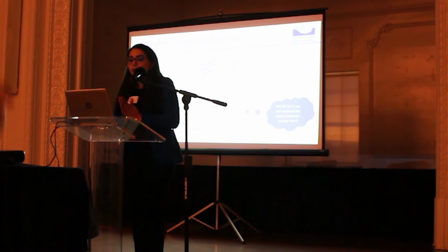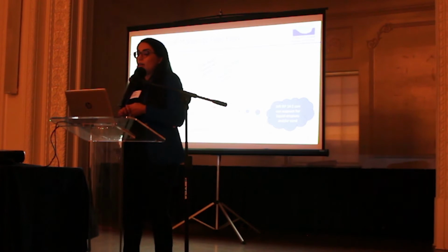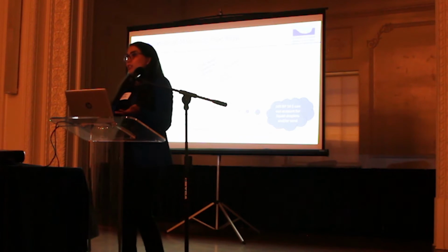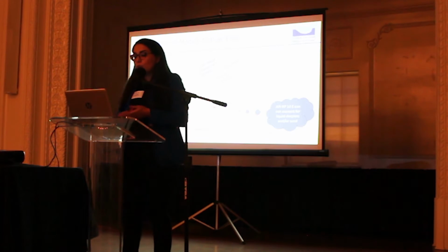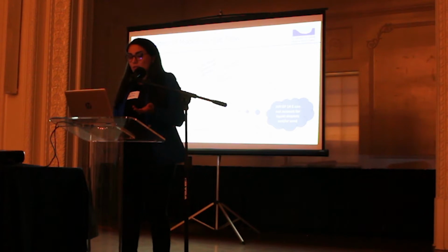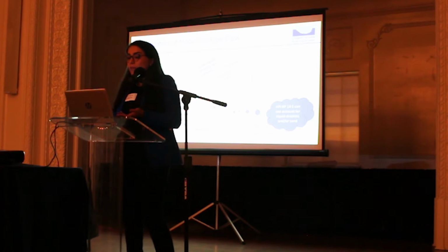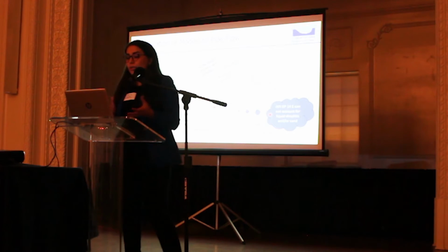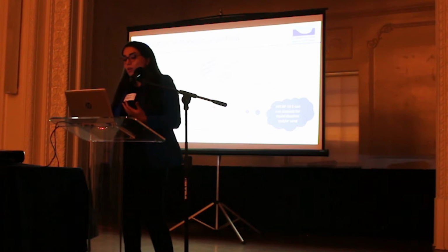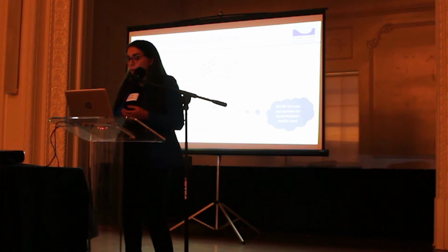So let me show you some slides that say how the API-RP practice was not doing a good job in many different cases. Okay? So for example, on this graph, we have erosional velocity on the vertical axis and pressure on the horizontal axis. And the red line shows the API-RP 14E. At ECRC, we developed models to look at droplet models of erosion without particles or when droplets contain particles. And as you see, the API model could not account for liquid droplets or sand. So, when you look at these models that take that into account, you see how this is diverging from what it could actually be.